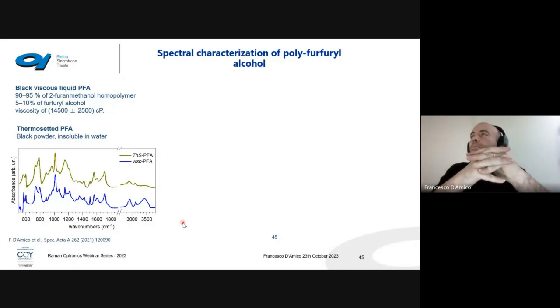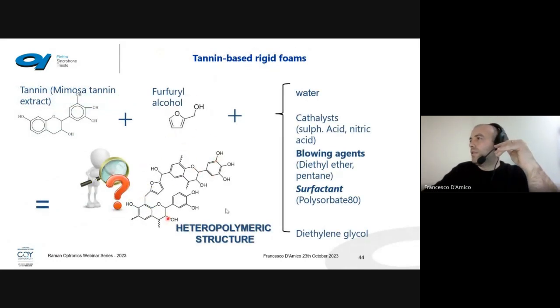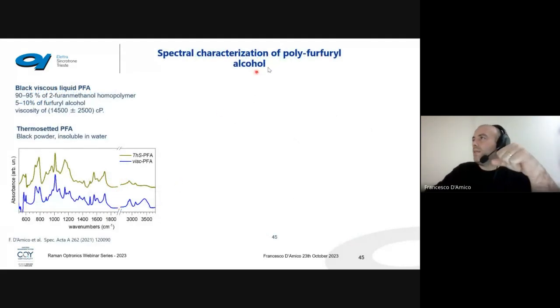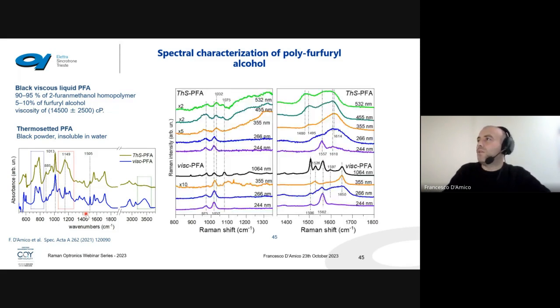First of all, we analyzed the behavior of polyfurfuryl alcohol, because furfuryl alcohol polymerizes inside here. And then we study polyfurfuryl alcohol separately to understand how it behaves. We can have black viscous liquid polyfurfuryl alcohol or a thermosetted one. Basically, we expect that in the previous sample we have a combination of both, but we don't know if the composition in the heteropolymeric form is similar to the black viscous or to the thermosetted one. We studied it separately. The problem is that when we study the FTIR spectrum, the spectra are very similar, apart from small differences, and we are not able to infer about this variation.